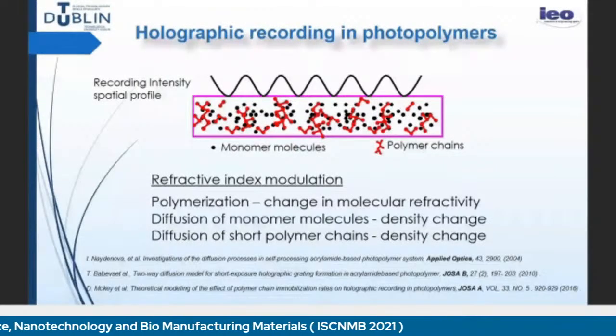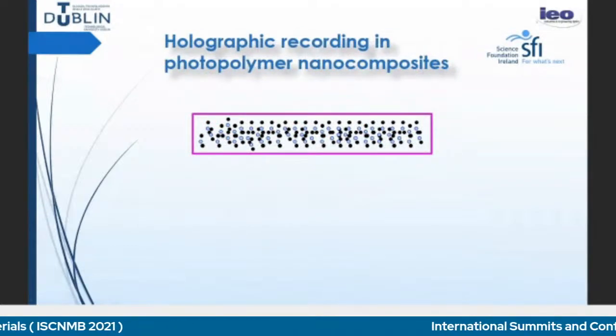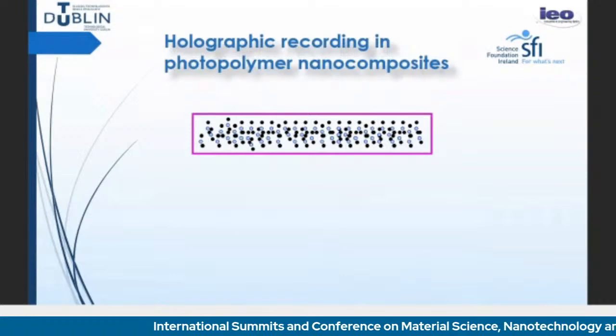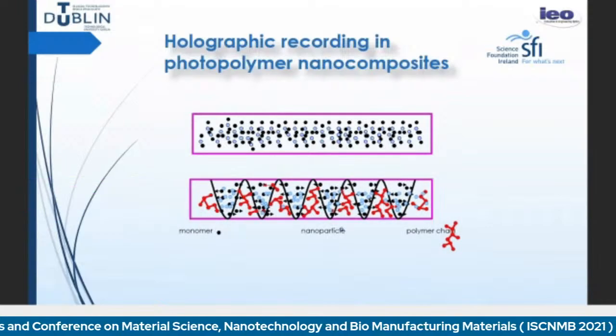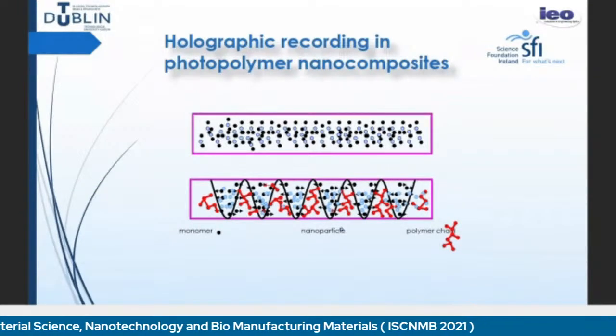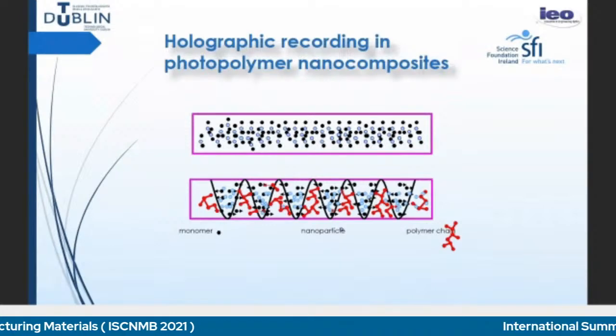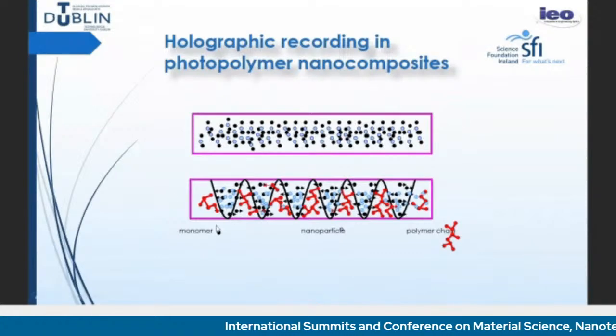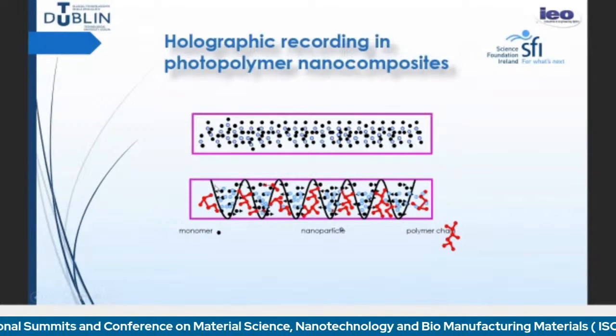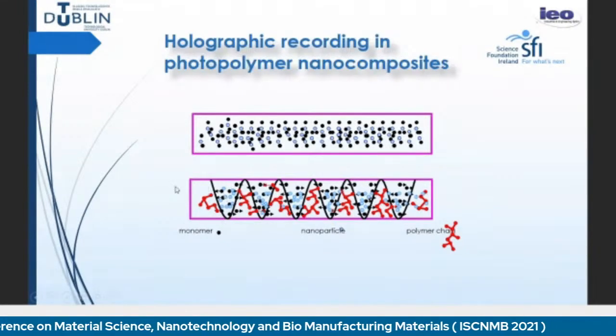This leads to deteriorated performance at very high spatial frequencies. In nanocomposites, in addition to the monomers, we add nanoparticles, which are typically very small, a few nanometers, in order to avoid scattering. As a result of the holographic recording, we redistribute the nanoparticles, so their concentration is spatially modulated. In our own experience, we have observed that the nanoparticles are positioned in the areas where there is a low polymer concentration, so they are expelled to the dark fringe areas.